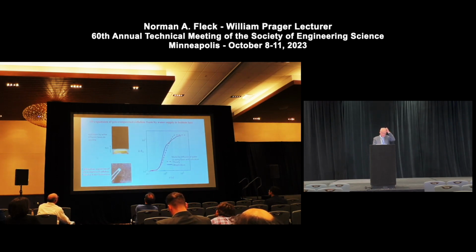Well, how do we analyze such a behavior? The initial steps would be, first of all, to separate out. I've just taken a little bit of the cellulose foam here in the compressed state. I've dropped it in water, and you can see this huge expansion by a factor of 10 or more. So that's the expansion phase, just due to hydration of the foam. Suddenly, when I say suddenly, it's between 0.1 and 0.5 seconds it takes for the foam to expand back to its initial state.